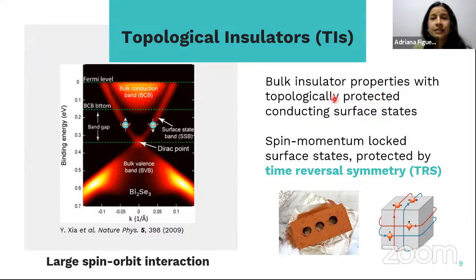with the existence of topologically protected conducting surface states. So what does it mean? It means that if we look at the band structure of a TI, we will see the bulk band gap, and the bulk band states that we see. But then at the same time we have some metallic-like surface states, in which the spin momentum is locked and protected by time reversal symmetry. So it's not only that it has some surface states which are metallic-like, but also they have these characteristics in terms of the spin momentum locking, right? And these characteristics are due to the large spin orbit interaction that these materials possess.